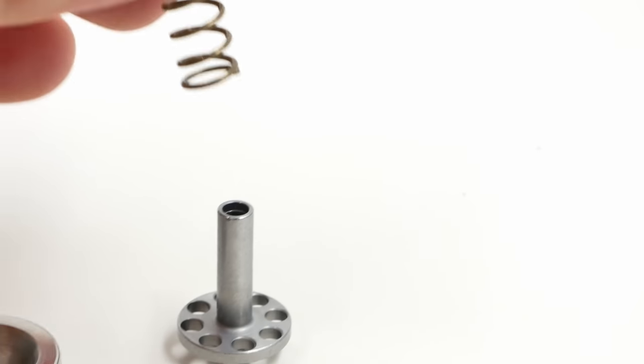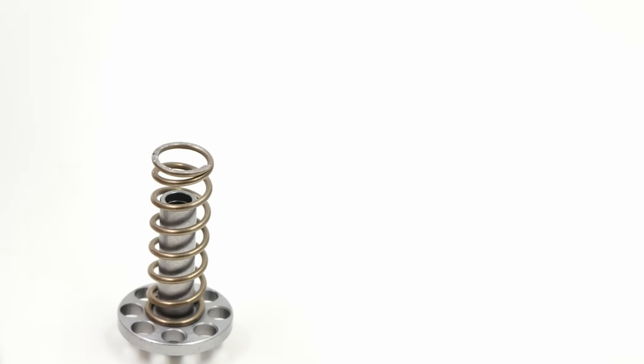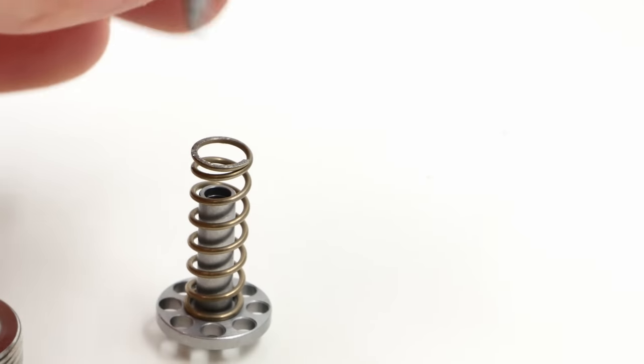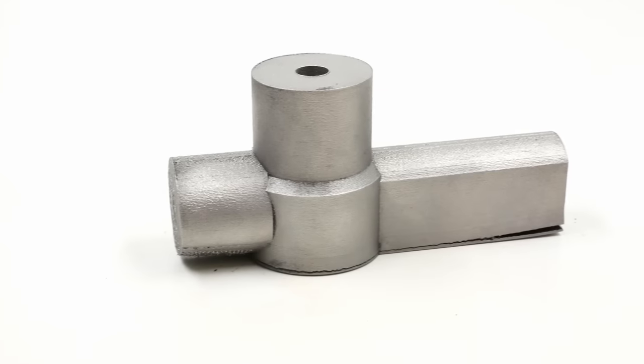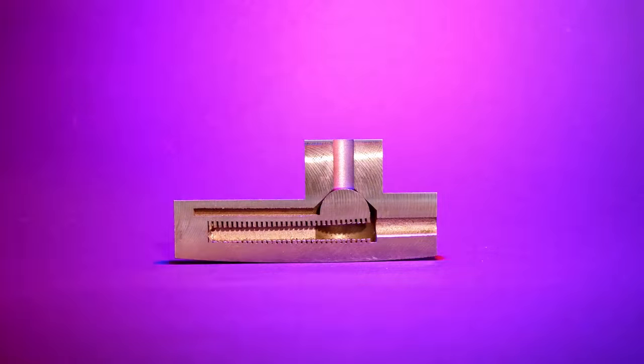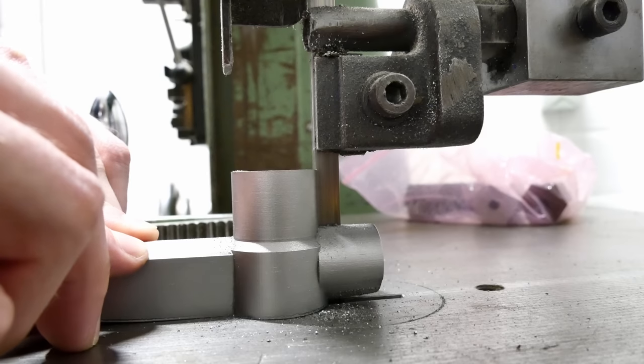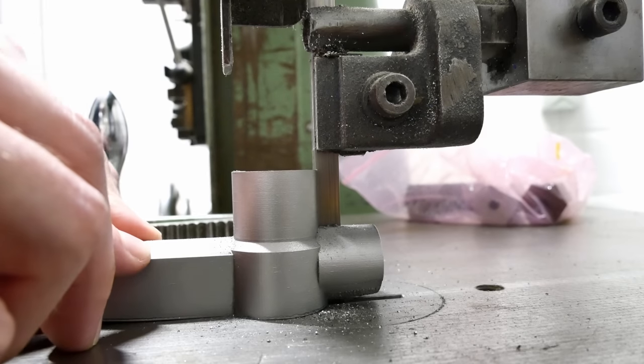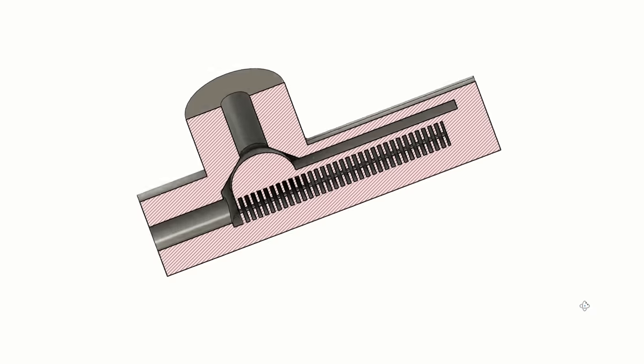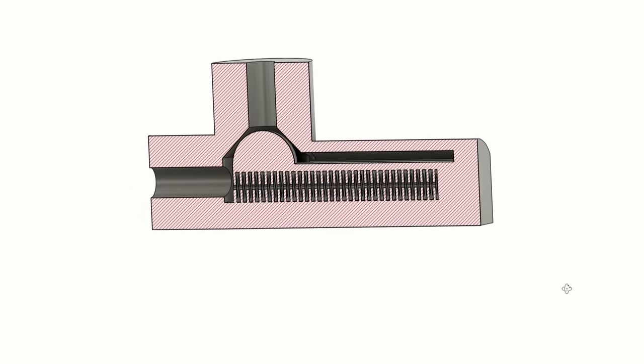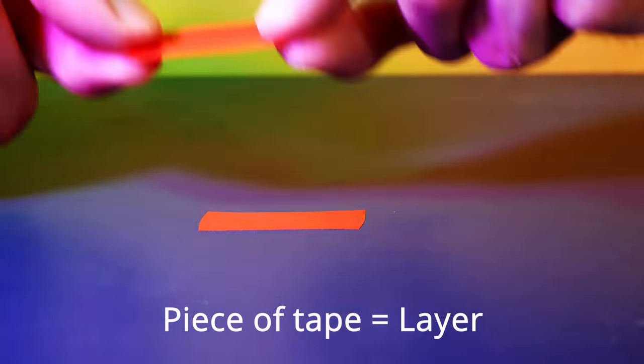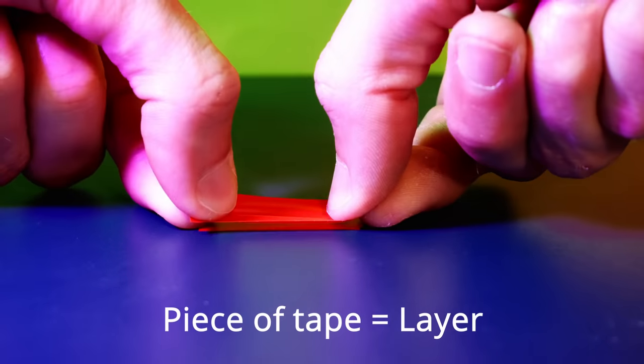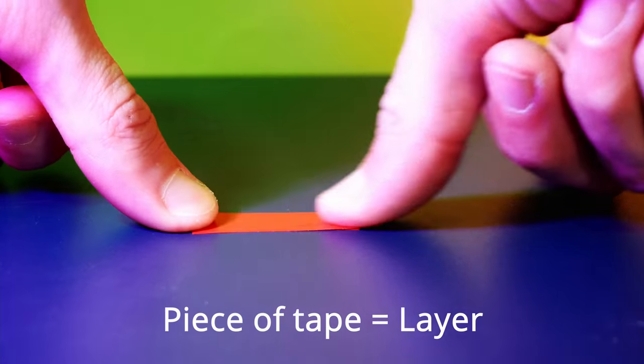You're probably noticing that this design does not have a spring nor the possibility to insert one, and while it's not necessary for a check valve to function, it does limit its use cases and it also affects its response performance. So with that in mind I designed this. This is what I call the cantilever check valve. It is called that because when you see it open you will see that there's a sealing body at the end of a cantilever. When printed, the cantilever is held straight by support structures, but during printing internal stresses build up due to thermic expansion and contraction.